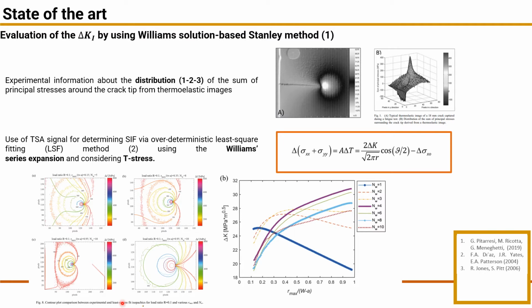Even in the work of Pitarresi et al., an over-deterministic least squares fitting method using the Williams series expansion is adopted. In this case, T-stress was considered in the analysis, and the stress intensity factor was determined also as a function of the number of terms in the Williams series function, and the extent and position of the area for data input were also assessed in this work.